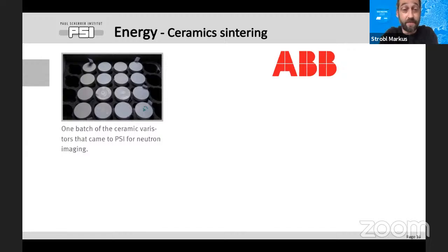This is a relatively recent example where we worked for ABB, which is a very strong local but also international company. What we did here, we were looking into ceramic varistors and in the sintering process. So ABB had the problem that depending on how they sintered and how many pieces they had in the oven, they got different results on how good the binder was burned out of these varistors. And this, of course, impacted the quality.